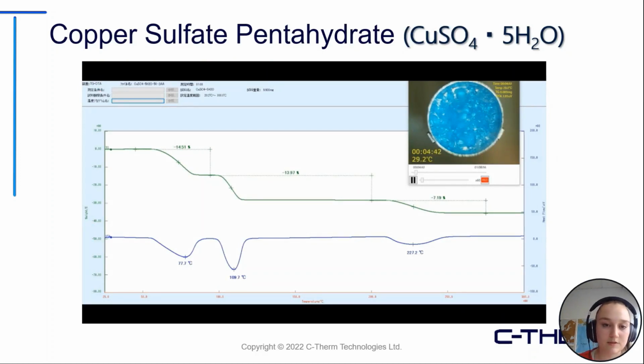Okay, so copper sulfate pentahydrate dehydrates in 3 steps. The first 2 steps, you can see about a 14% mass loss. This represents two water molecules. So it's lost 2 water molecules in the first mass loss, 2 water molecules in the second mass loss. And you see that third mass loss, which is coming up about minus 7%. So it's losing the final 1 water molecule.